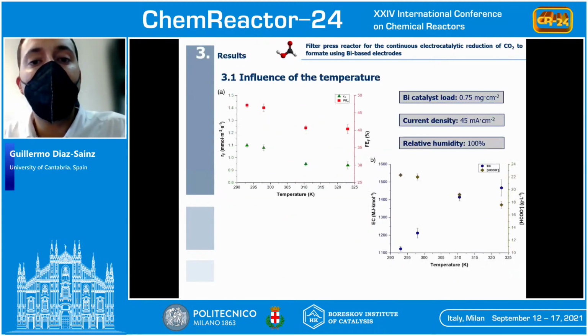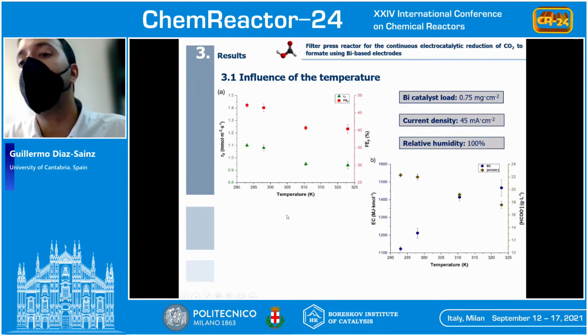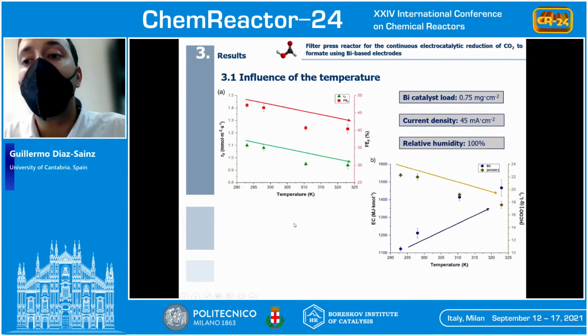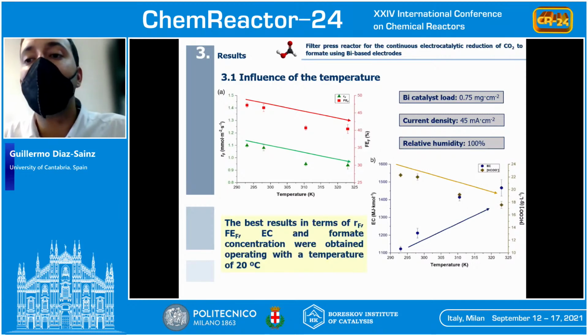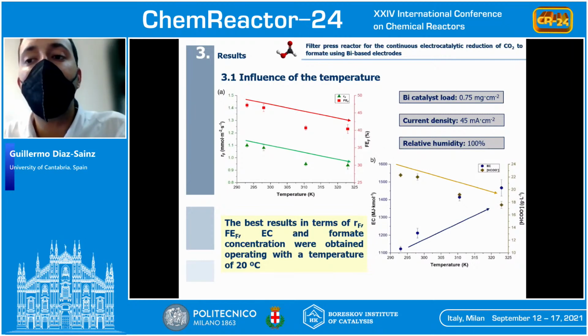If we start with the influence of the temperature, all the experiments were carried out with a bismuth catalyst loading of 0.75 milligram per square centimeter, a current density of 45 milliampere per square centimeter, and a relative humidity in the carbon dioxide humidified input stream of 100%. Several tests were carried out in a temperature range between 20 Celsius degrees, or ambient conditions, and 50 Celsius degrees. We can observe that increasing the temperature from 20 to 50 Celsius degrees, all the figures of merit used to assess the performance of the process, that are the formate rate, formate concentration, energy consumption, and Faraday efficiency, were damaged. For this reason, the best temperature for the electrocatalytic reduction of carbon dioxide to formate was 20 Celsius degrees, and in the next sections, all the experiments were carried out at this temperature.